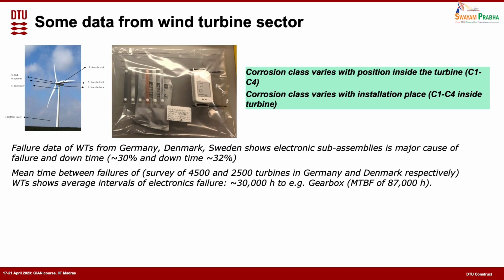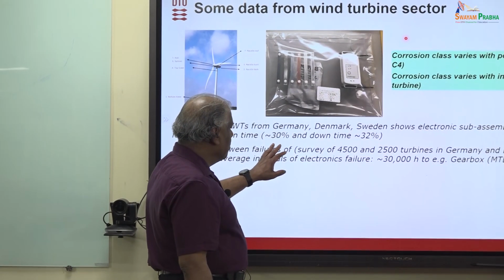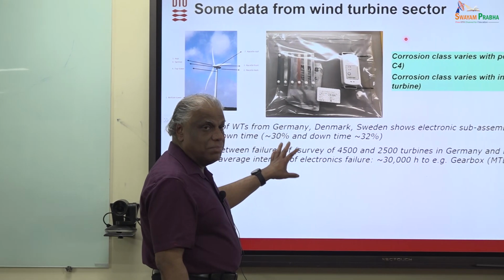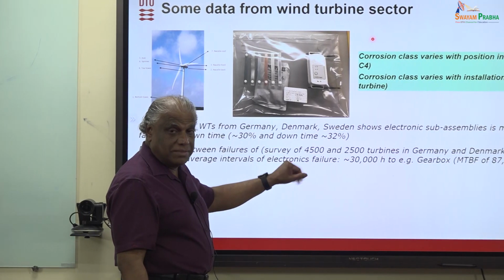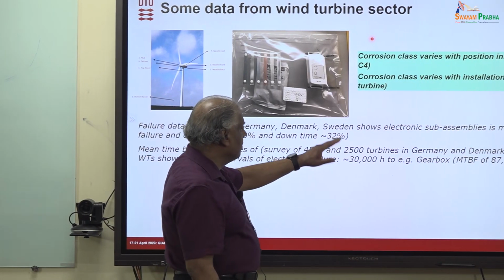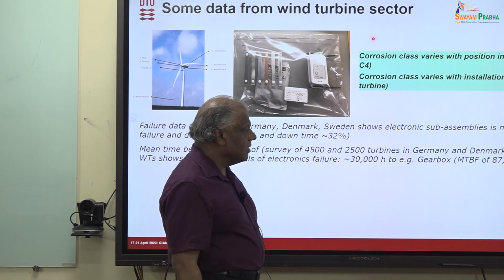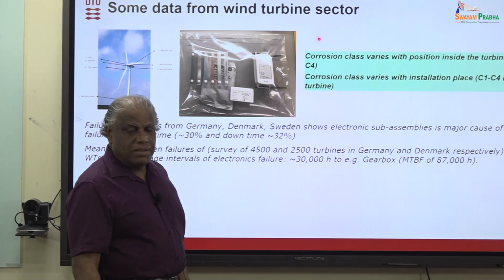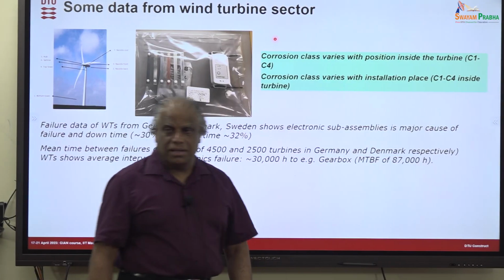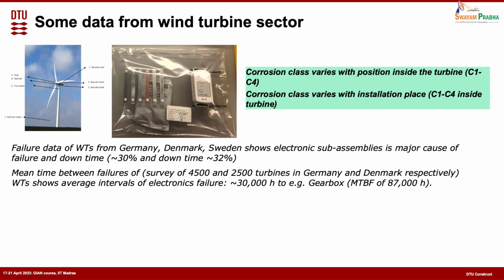To show you why this is important, yesterday I mentioned the wind turbine measurements. The statistics show that in Germany, Denmark and Sweden, the electronic sub-assemblies fail fast compared to the other components. The mean time to failure for the electronic sub-assemblies is around 30,000 hours, compared to that of the gearbox, which is around 87,000 hours. That is one thing I am showing, the importance of the electronics and why they need to be taken care of. I think we can leave it there.